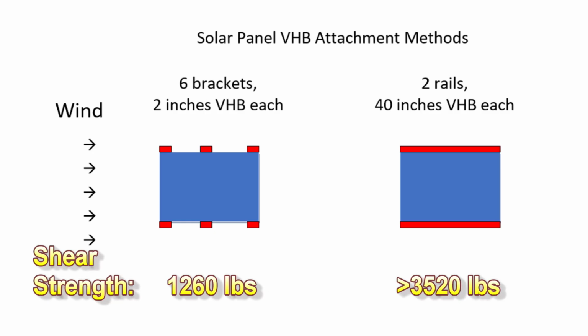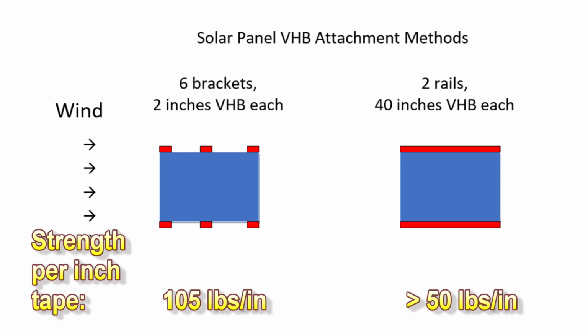Wow. A final note. The 40-inch rail was much stronger, but on a per-inch basis, not so much. I believe this is due to repeated tests on the same 40-inch rail, which may have weakened it, and to pegging the scale, so I really don't have a peak value. It was likely much higher.